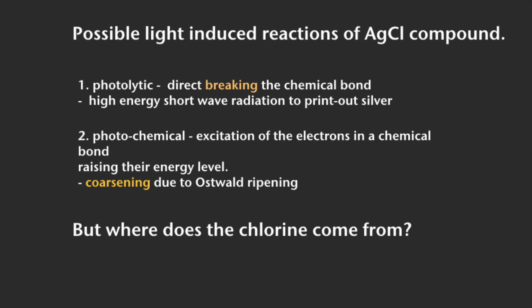So what I believe here is not a deposit of silver causing the haze, a redeposited silver, but rather the silver chloride halogen on the plate is ripening into a larger, more visible crystal. Which explains the ripening is going to happen. It wants to happen whether it's in the dark or whether it's in the light. Which explains why they come out of the box in a hazed condition. But it can also explain why the haze can be promoted by light energy. It just quickens up